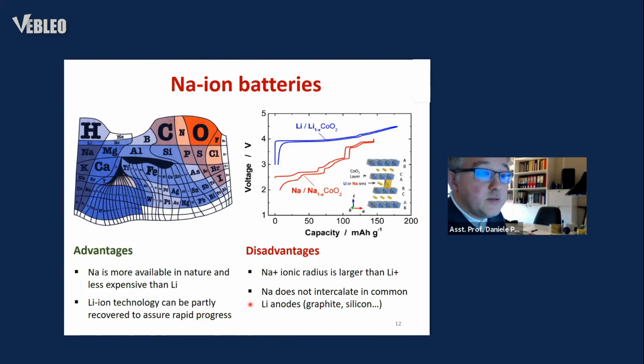On the other hand, the performance of sodium-ion batteries is expected to be slightly worse than lithium-ion batteries due to the dimension of the sodium ion, which is larger than the lithium ion. Another weak point is that sodium does not intercalate in common lithium anodes, such as graphite and silicon, and this requires some research on materials.